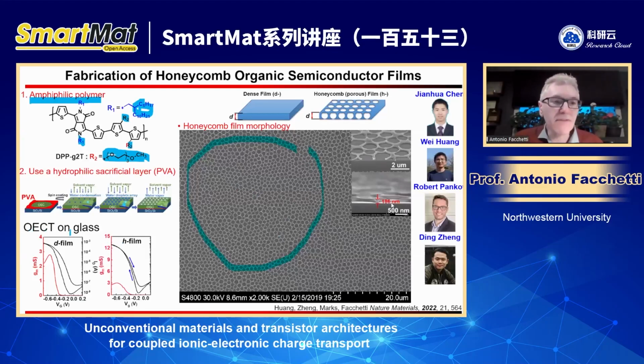So this polymer, we made dense film, we made this whole honeycomb film, and then we made the device on glass. And the device on glass has been fabricated by, we made the film on PVA, and then we put the film on water, PVA dissolves, so the honeycomb or the dense film floats in water. Then we transfer them on the OECT platform, on the contacts.